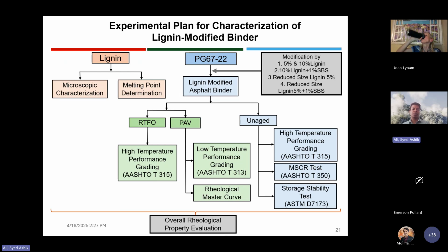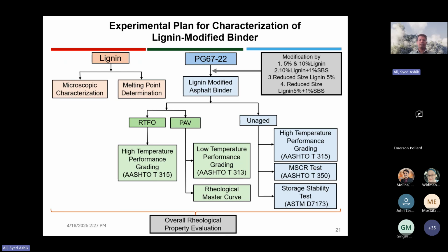So to begin with, to modify our asphalt binder with rice husk derived lignin, we collected a commonly used PG67-22 binder. I know people from Oklahoma do not recognize this because we do not have a PG67 grade, but it's common in Louisiana, and they choose to have a very commonly used Louisiana PG67-22 binder. So we get that, and we wanted to modify that binder with 5% and 10% lignin.